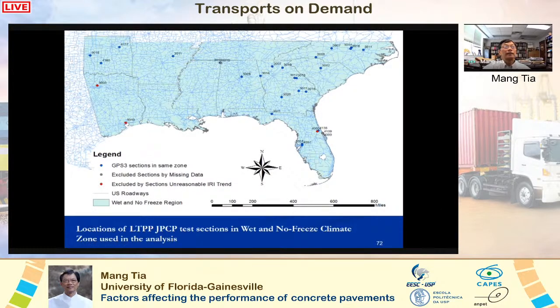And there were a total of 26 jointed plain concrete pavement sections in the region that is similar to the condition in Florida. It's known as the wet and no freeze climate zone. Okay, and this map shows the location of the pavement sections that we got the data from. And two of them, the test sections marked in red, were excluded due to incomplete data. Thus, only data from 24 test sections were used in the analysis.